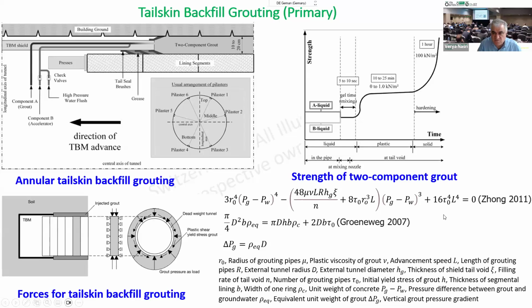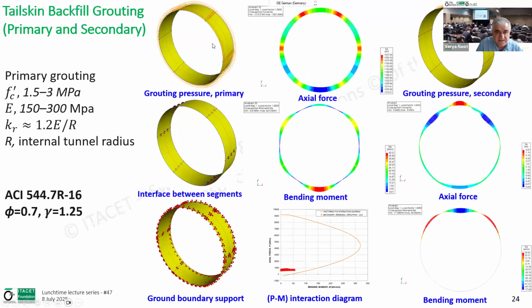So then we use this formula to solve for pressure of the grout minus pressure of the water, how much it should be more. And then we use the equilibrium in vertical direction based on weight of the liner, buoyancy of the grout, and then shear stress of the grout. And we find the unit weight of the grout, and based on that, we find the grout pressure gradient. And from that, we use this model of the ring with that pressure and its variation applied.